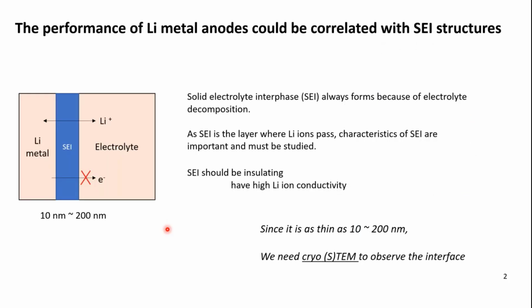However, developing lithium metal anodes is still challenging, as the interface in the batteries is not stable. The interface called the solid electrolyte interphase always forms due to electrolyte decomposition. As this interface controls transport of ion and electron, we need to understand what's going on in this interface. As the SEI turns out to be as thin as a few tens of nanometers, sometimes it can grow up to 200 nanometers. So as it is at the nanometer scale, we need to use electron microscopy to understand this feature.